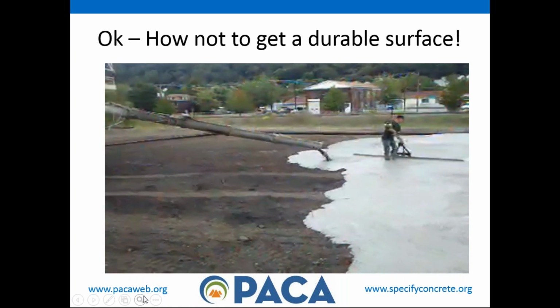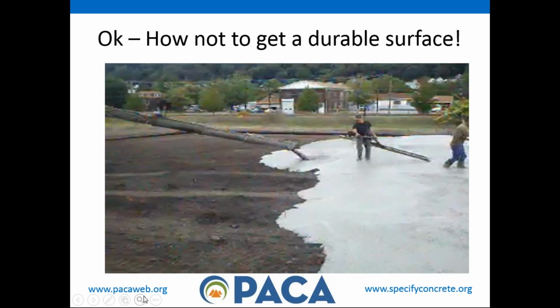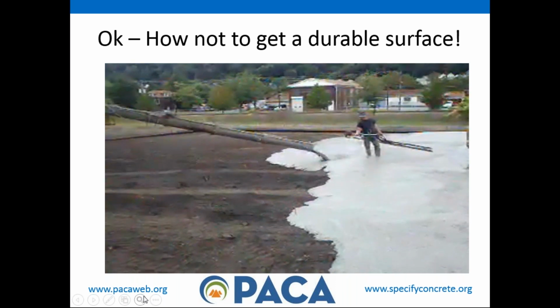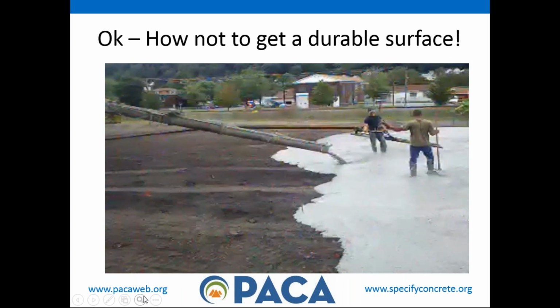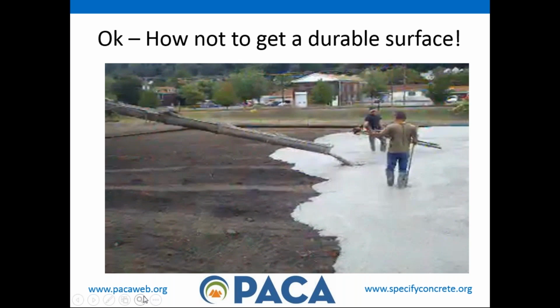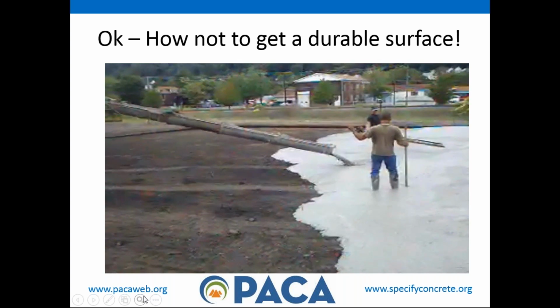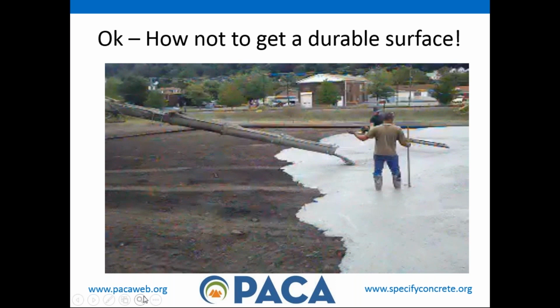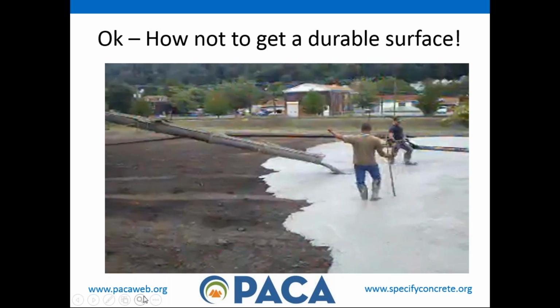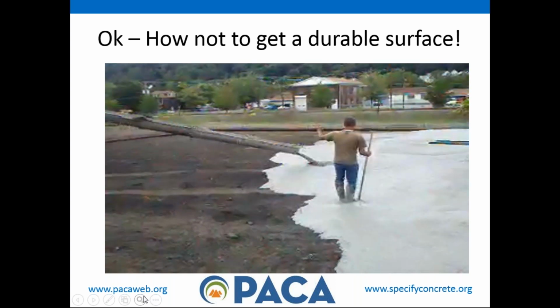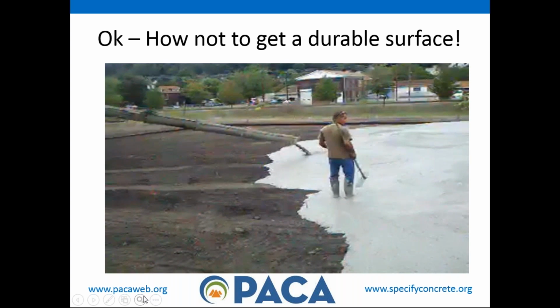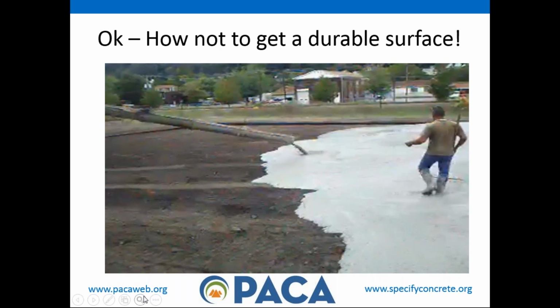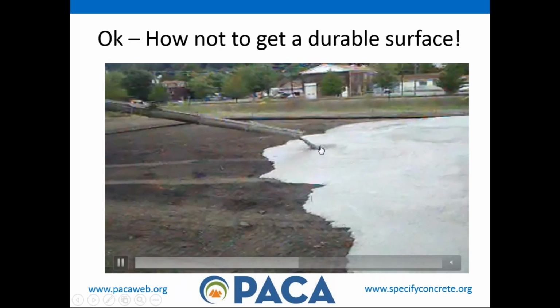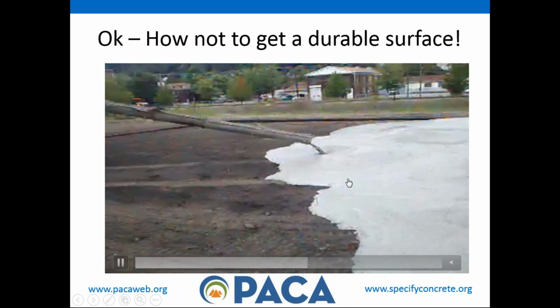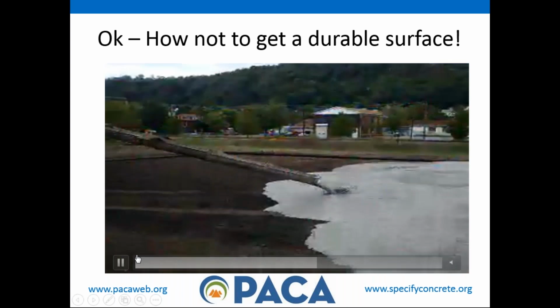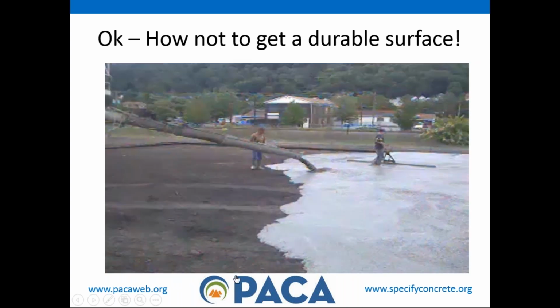This is just guys that need to pour it wet because they didn't have enough help, and they backed themselves into a corner. They had no issue with us filming this. I mean, you can see how wet it is. And just for the record of the video and the recording we're listening to, that is not Super P in that mix. That is all water slump. And as you can see, as the coarse aggregate hits it right here, it disappears. It's sinking to the bottom. And this will most certainly fail. So I'm going to stop that and move us on to the next one.